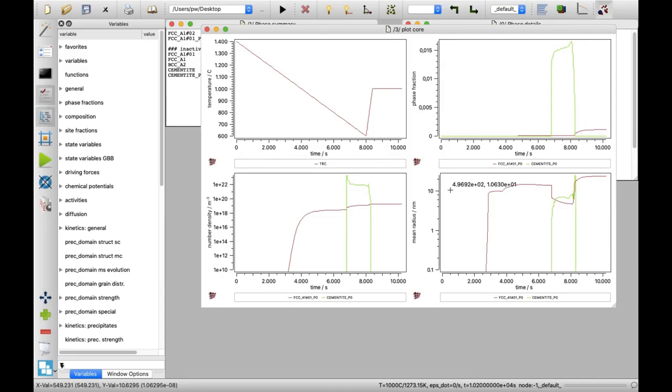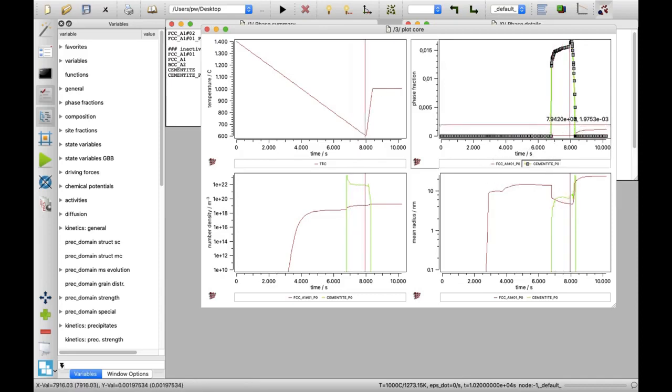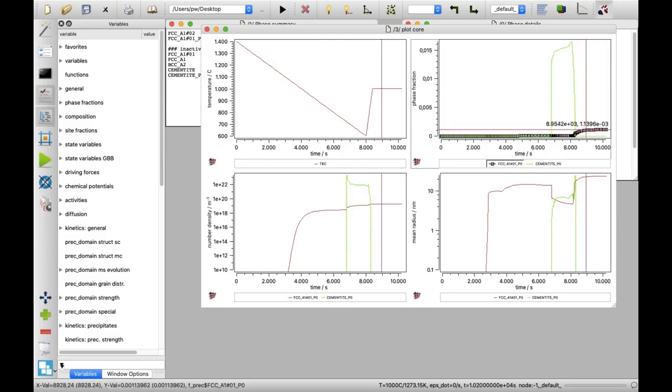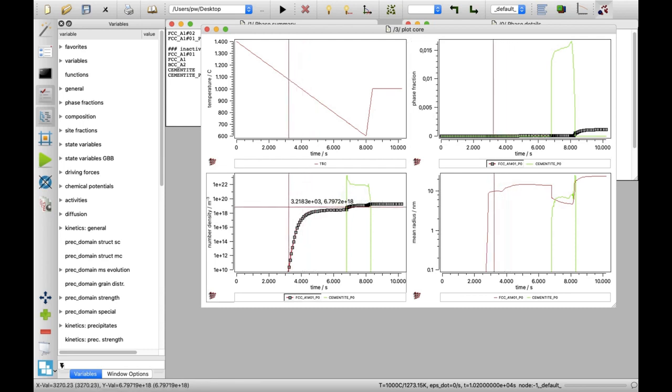new window. The phase fraction plot is dominated by the cementite curve appearing in the temperature range of ferrite precipitation domain. Next to it, the increase in niobium carbide phase fraction during the isothermal holding at 1000 degrees Celsius can be also observed. The plot of precipitate number densities shows that the precipitation of niobium carbide occurred already in austenite during cooling, but a further nucleation wave is observed in ferrite, when the carbon supersaturation increases. Additional nucleation wave appears also after the cementite dissolution.